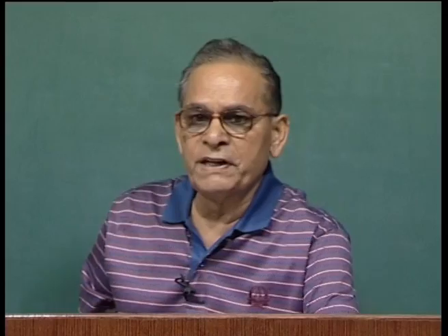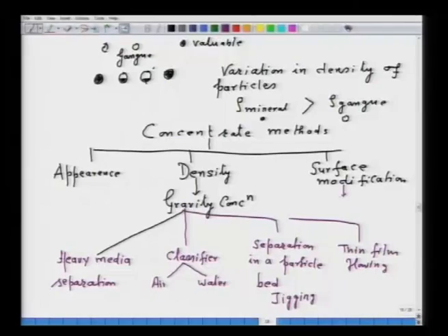Now, the surface modification, that means you modify the surface of the mineral. You are not chemically affecting the mineral, you are modifying the surface of the mineral, so that it becomes hydrophobic or hydrophilic. And this method is called flotation.